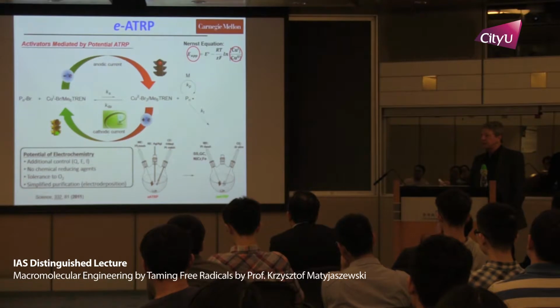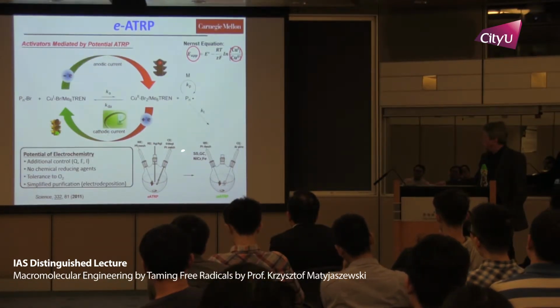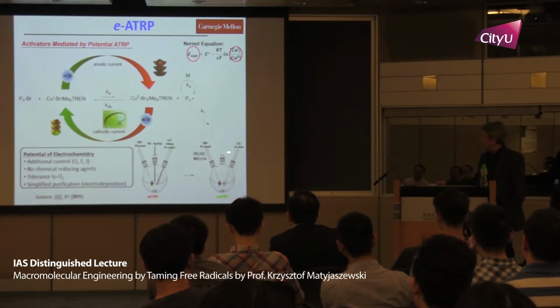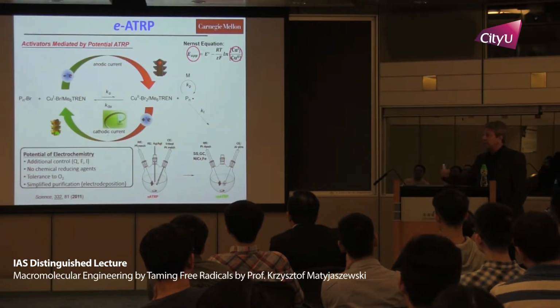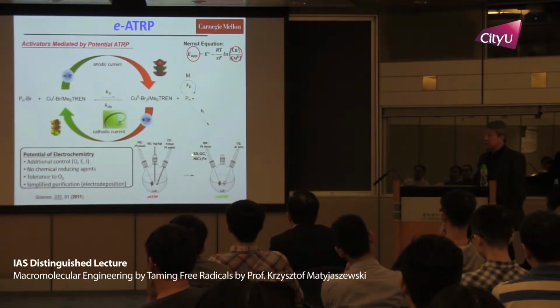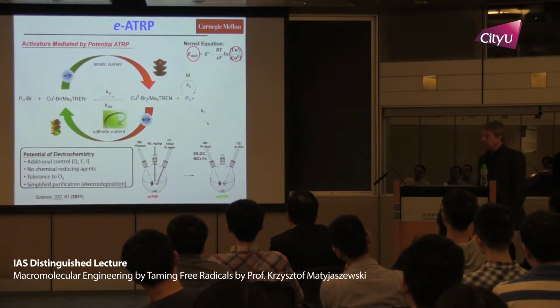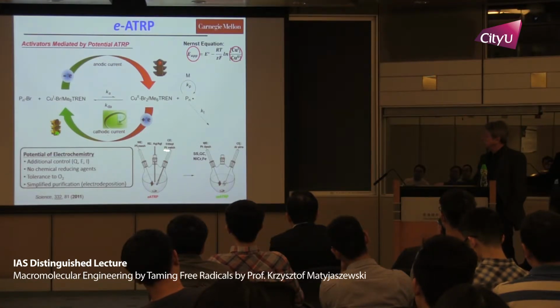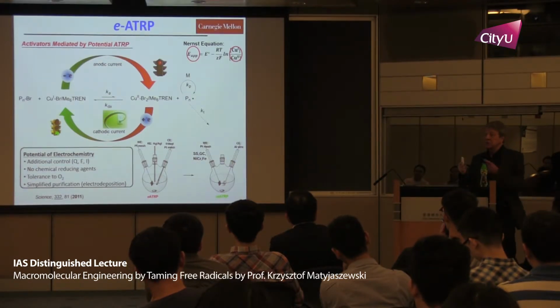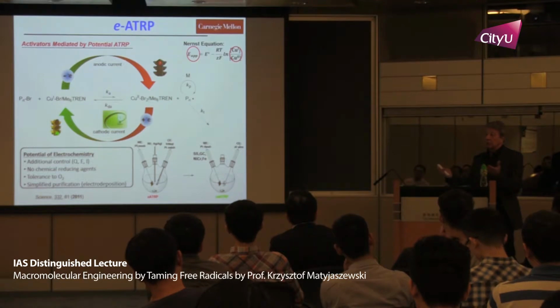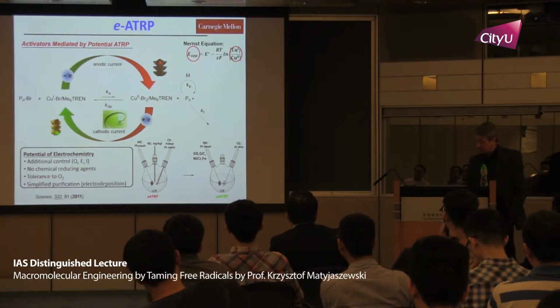And then progressively, we switch to simpler and simpler systems. For example, we replace this counter electrode platinum mesh with the aluminum wire. It acts as a sacrificial electrode. No more separation needed. Instead of platinum here, we now use stainless steel or glassy carbon. And in fact, you don't need to use a potentiostat, which costs $10,000, but you can use a current generator for $100, or you can use an AAA battery for $1. And all of this really works very nicely.